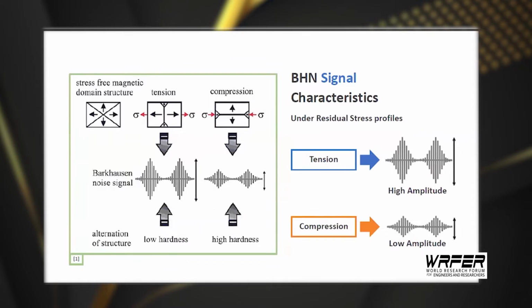The signal features of the BHN signal are influenced by differences in material properties such as hardness, and by external force. The amplitude of the BHN signal received under compression is smaller than under tension force. This research aimed to propose a suitable method for measuring the residual stress of AISI 1050 sheet steel according to the ASTM standard. The BHN system was used to measure and was calibrated with the XRD, or X-ray diffraction, technique.